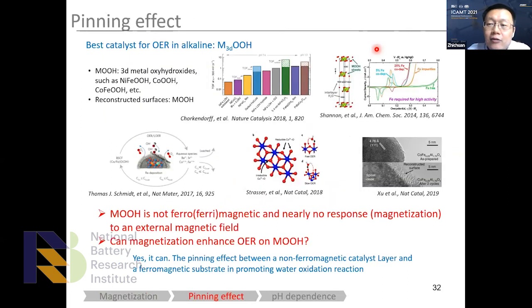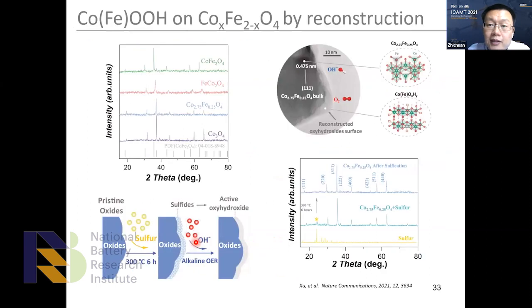Right. So now let's see how we can extend this principle to real applications. For example, most of the best catalysts for OER in alkaline are not ferromagnetic oxides. They are transition metal oxyhydroxides. You can see from these benchmark works, right? All of them are not ferromagnetic. They are paramagnetic or antiferromagnetic, but at room temperature they are paramagnetic. So can we use that? Okay. So now we will introduce the pinning effect. We make the deposit by reconstruction, controlling the reconstruction.